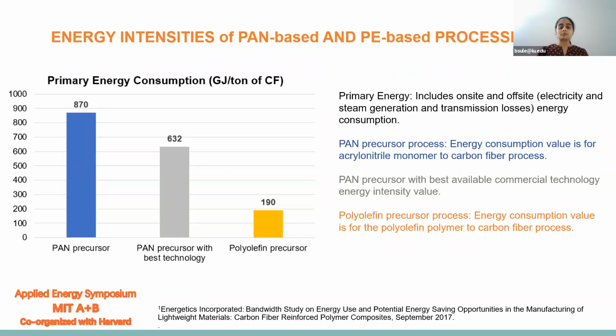This data is from a bandwidth study report made by Energetics Incorporated for the Department of Energy. So for the PAN precursor process, the primary energy consumption is around 870 gigajoules per ton of carbon fiber. If the best available technology is used, then this can be reduced to 630 gigajoules per ton. If further the polyolefin precursor is used, then this energy consumption can be brought down to 190 gigajoules per ton